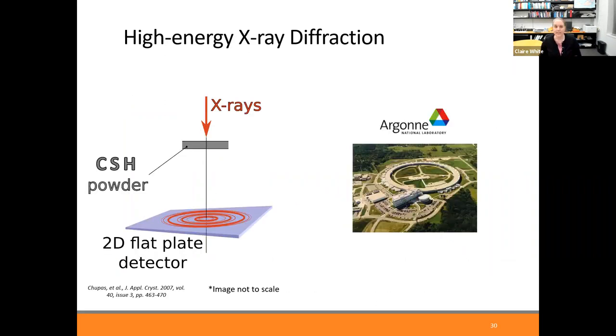What we also did was X-ray pair distribution function analysis on the same gels. And to do this technique, we went to a synchrotron. We specifically went to Argonne National Lab, the Advanced Photon Source. And you can think of it as conventional X-ray diffraction, but on steroids. I don't know if that's a good term.